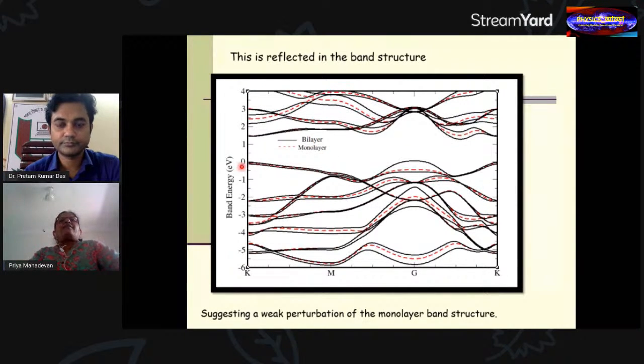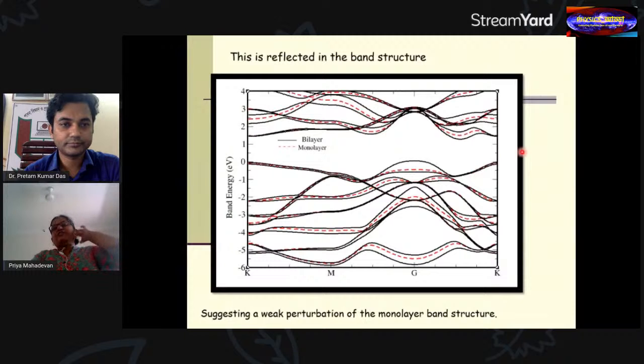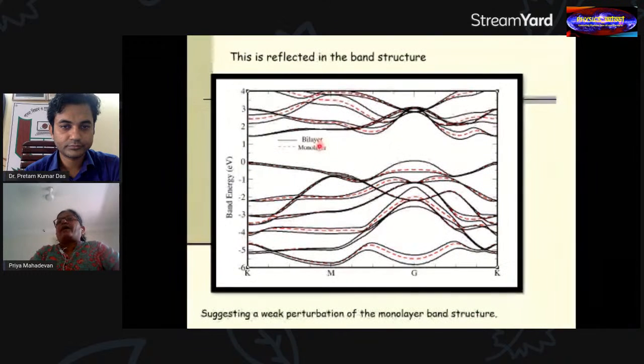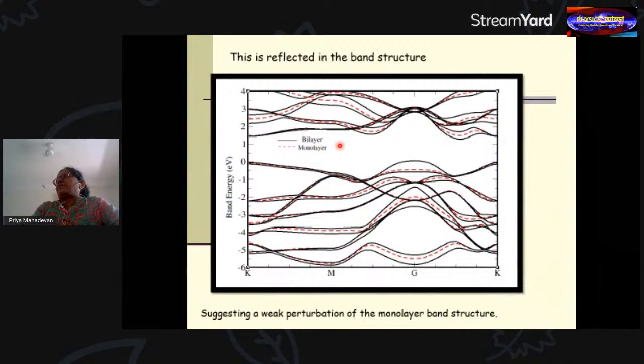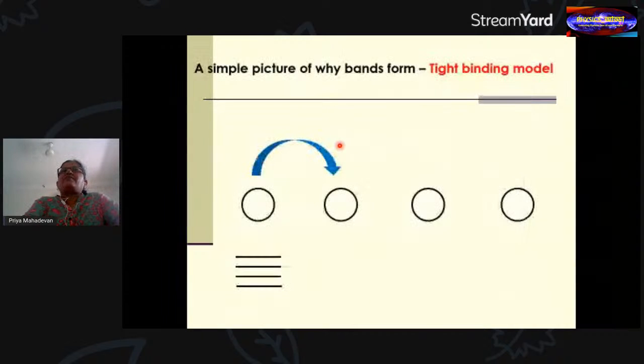Okay, so if you look at these band structures, what you can see is that in most of the region there's hardly any perturbation of the monolayer band structure, even though I brought in the next layer and formed the bilayer. That is exactly what I'd expect, because being able to pull the layers apart actually means that the electronic interactions between the two layers are quite small, and that has to reflect in its properties also.